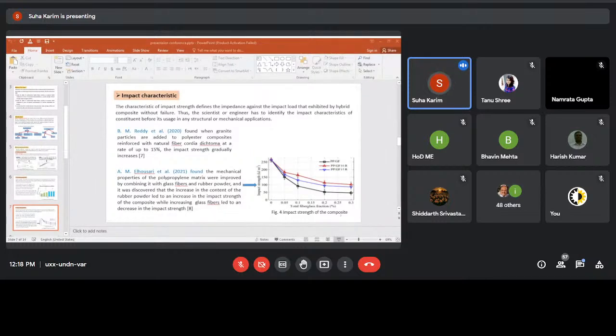In another study, Al-Hawsari in 2021 found that the mechanical properties of the polypropylene matrix are improved by combining it with glass fiber and rubber powder. They discovered that increasing the rubber powder increases the impact strength, whereas increasing the glass fiber leads to a decrease in the impact strength, as we see in one of the results of this research in figure 4, the impact strength decreasing with increasing fiber glass fraction percent.